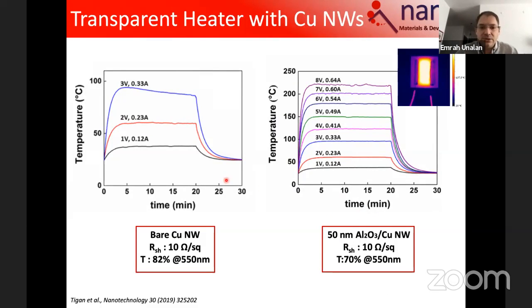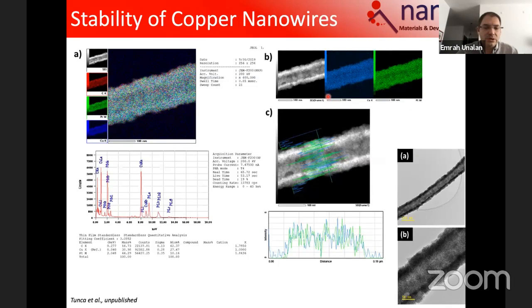And we immediately use this idea in heaters. So in a bare unprotected copper nanowire thin film, you can go to a high temperature as high as 100 degrees Celsius. But if you put 50 nanometers of aluminum oxide, you can go to excess temperatures of 200 degrees Celsius without any damage. So it also improves the thermal degradation history of copper nanowire networks.